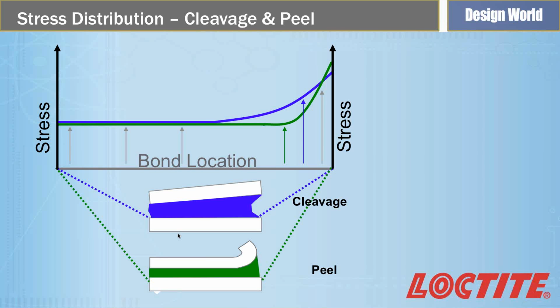Lastly is a peel or cleavage force, and this is really where you're pulling up one side and holding the other constant. And the only difference between peel and cleavage is whether or not your substrates are rigid. If it's rigid, you have cleavage. If it's flexible, you have peel. And the takeaway here is you don't want these. These are the most aggressive forces you can put on an adhesive because you have concentrated all the stress on that leading edge of the joint. And when it starts to fail, it just keeps moving its way down the end. So you definitely want to try and avoid cleavage and peel in your design if you can.